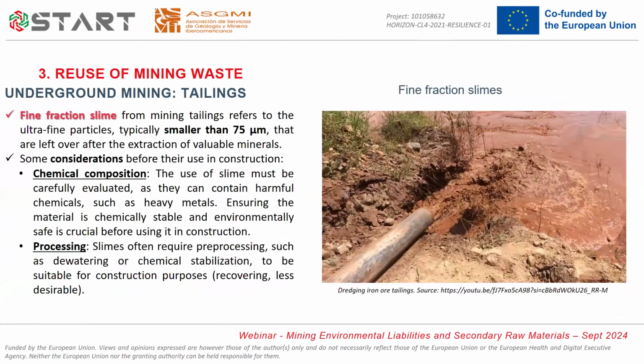In the case of fine fraction, the slimes, they have a special size and composition. So before using them in construction materials, we need to make some considerations. The most important consideration is that these materials must be chemically stable and environmentally safe. That means that they must not have heavy metals.